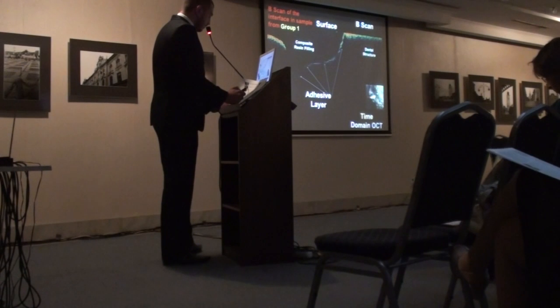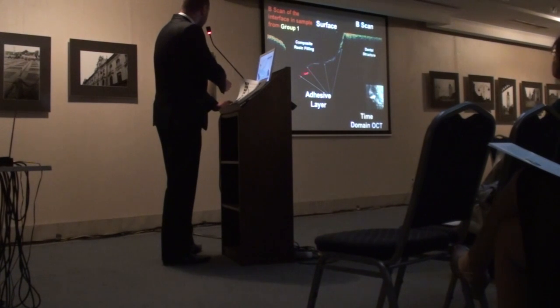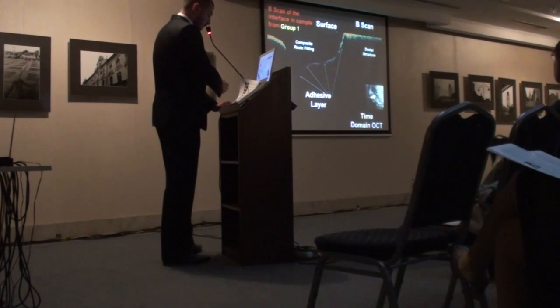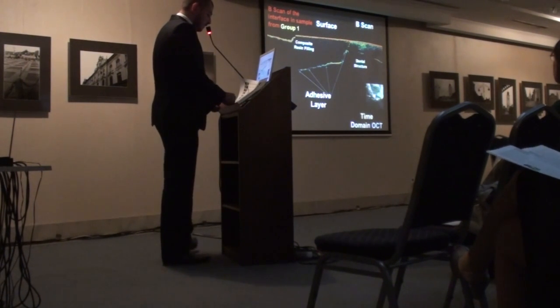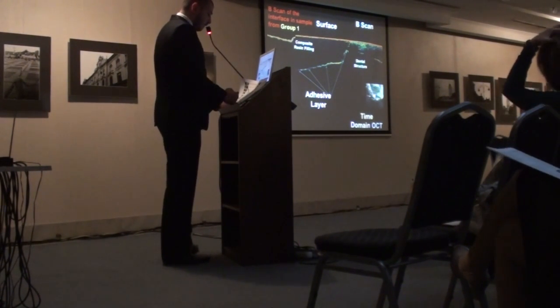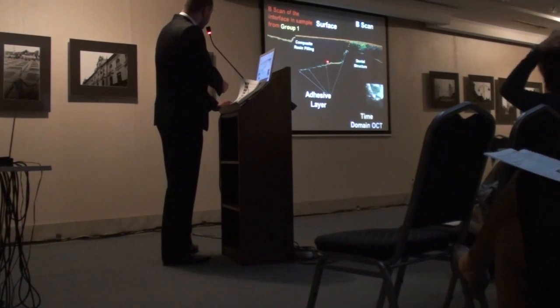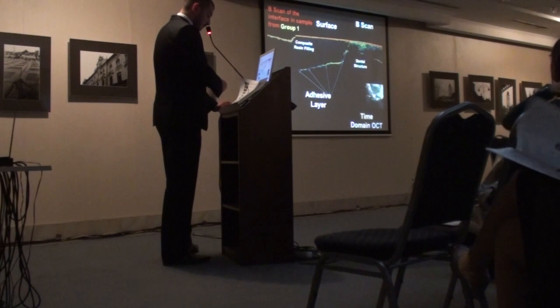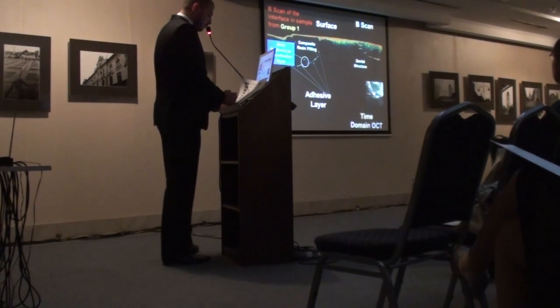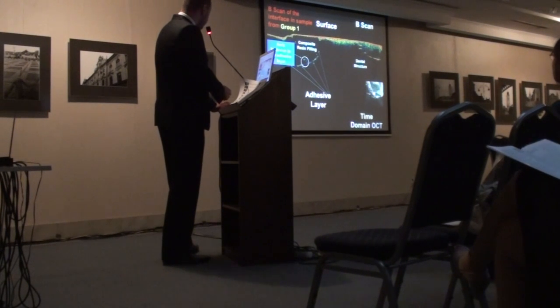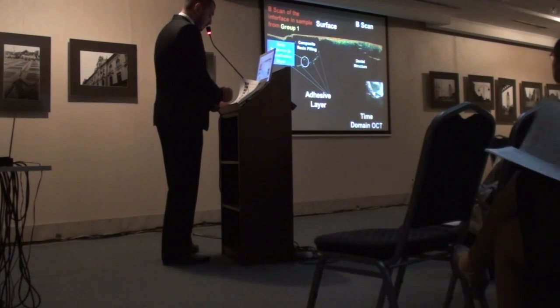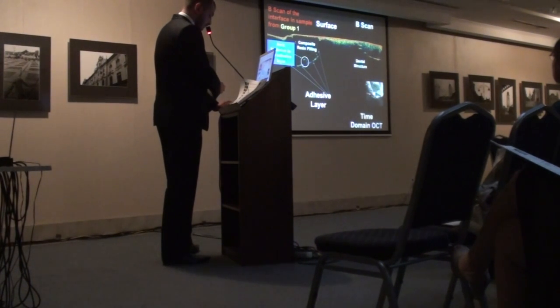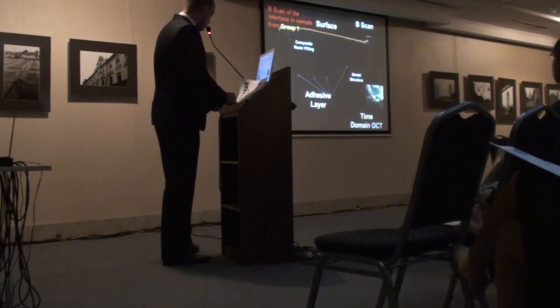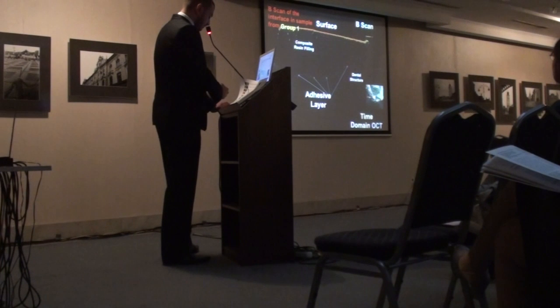8% of zirconia concentration was added. The adhesive layer seems to be much easier to evaluate. Good contrast obtained between the dental structure, adhesive layer, and composite resin filling after modified adhesive was used. Air inclusions in the modified adhesive layer. Now these differentiations can be made much more easily. Good interfaces between the cavity wall, adhesive layer, and resin composite filling.